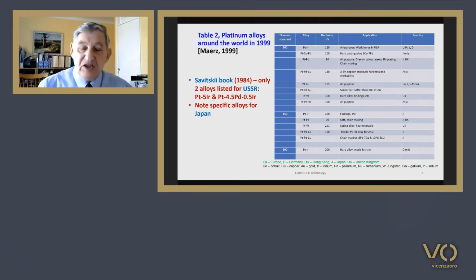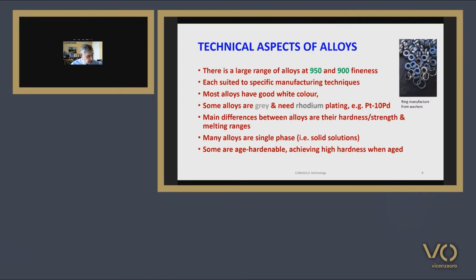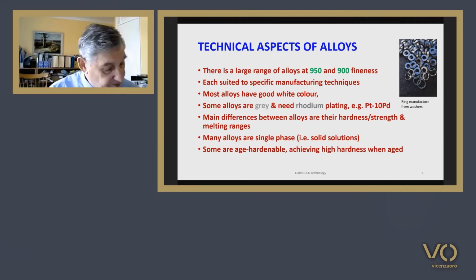Let us look a bit at the technical aspects of these alloys. We note that at 950 and 900 fineness qualities, there is a broad range of alloys available to the jeweller, each suited to various manufacturing techniques. All have a good white colour, although some may benefit from rhodium plating, for example the platinum 10% palladium alloy, to give a brighter, whiter colour. The main differences between alloys lie in their hardness or strength and their melting ranges.